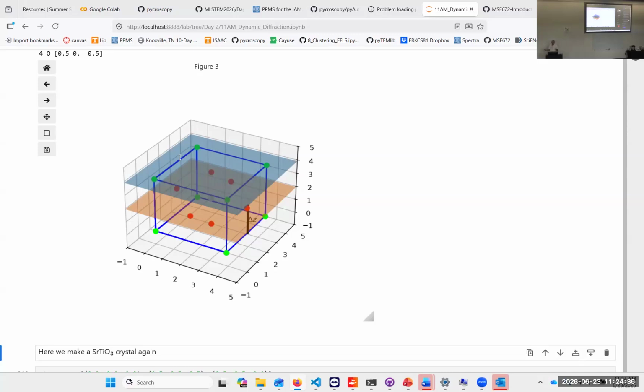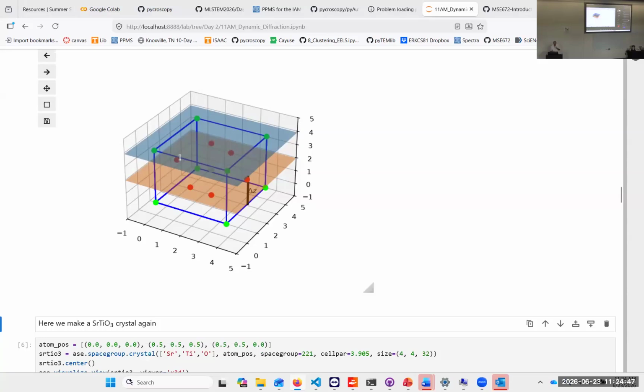We are going backwards and forwards between real space and Fourier space. So we always have to have relatively large unit cells so that we have good resolution in reciprocal space, because the dimensions of our object give us the resolution in reciprocal space. The larger that is, the better resolved the diffraction pattern we'll have.